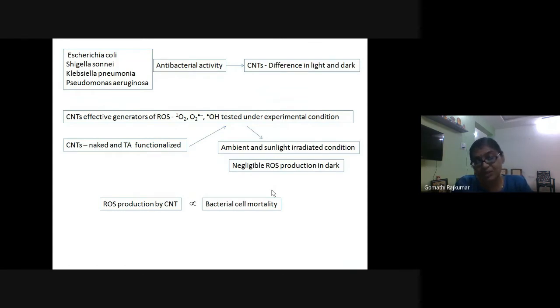So what happened exactly was, friends, we took 4 different bacteria, as I told you: Escherichia coli, Shigella sonnei, Klebsiella pneumoniae, and Pseudomonas aeruginosa, and we mixed them with carbon nanotubes, and we found out that these carbon nanotubes behave differently in light and differently in dark. In light, we could see that there was antibacterial activity, whereas in the dark, because all these conical flasks were kept in the incubation chamber, which used to also be a dark chamber, we could not find any antibacterial activity.